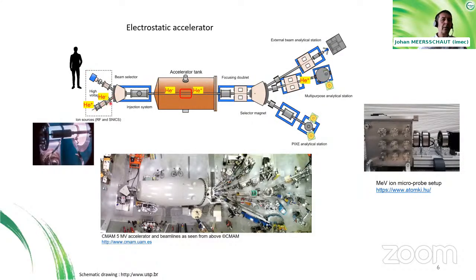Then these ions are brought into the anionic state, so you add an electron to them, and then you accelerate them typically to the positive terminal inside the accelerator. The acceleration voltage in the center of the accelerator is typically of the order of 2 to 5 megavolt. So you can understand that to achieve these high voltages, you need to insulate the terminal inside that tank with respect to the outside world. Otherwise, you would have discharges.